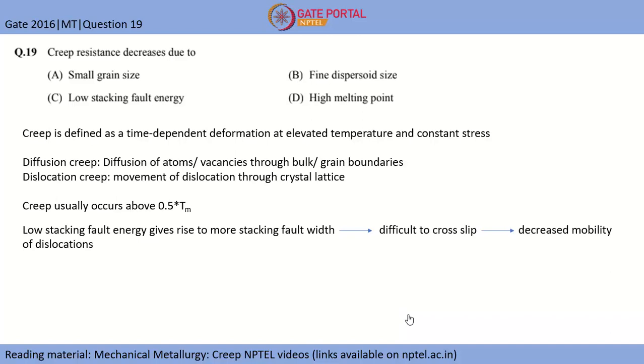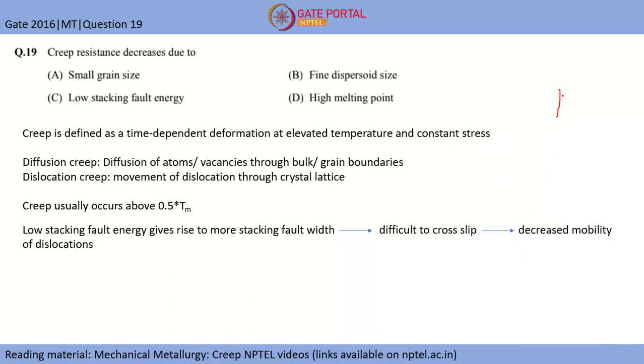Creep is defined as time dependent deformation at elevated temperature and constant stress. Let's say we have a material, we keep it at a temperature T and apply uniform stress, let's say compressive. P is the load applied, generating compressive stress throughout this cylinder, and we hold it for time T. Even below the yield stress, after a long time this material will try to deform or relieve the stresses caused by this load. Hence, this deformation caused by a constant stress at a higher temperature is basically creep.